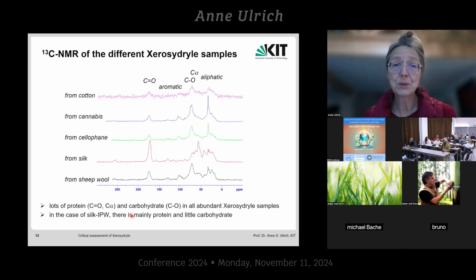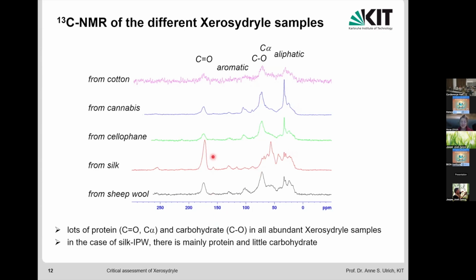Now we chose the carbon nucleus because carbon is so characteristic of organic material and biological material. And you see here a simple NMR spectrum of the different Xerosydryle samples from cotton, cannabis, cellophane, silk, sheep wool. And they have characteristic signals of proteins. These are the carbonyl signals, that's characteristic of protein, and the C alpha atoms here, but also of CO carbohydrate signals, as well as lipidic signals, aliphatic ones, over in this region. And in fact, most samples look pretty similar, in that they contain both proteins and sugars, carbohydrates. But interestingly, the silk sample, the Xerosydryle from starting material of silk, was a little bit more simple. It contained seemingly only protein here, but no carbohydrate. So we focused initially on the further NMR analysis of the silk sample from Naples.